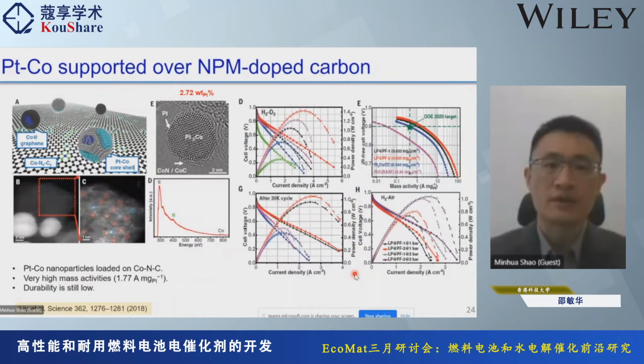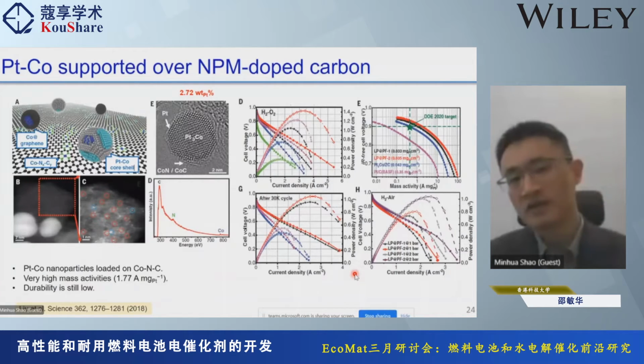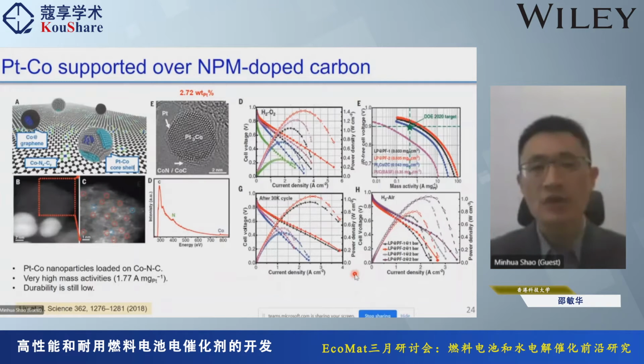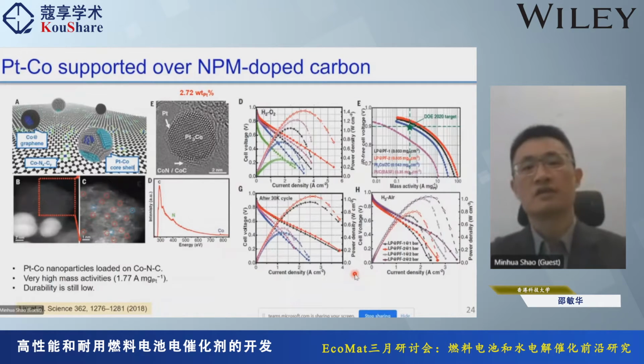So we're using this iron-based non-precious metal and platinum iron nanoparticles. So even though the iron-based non-precious metal has worse durability than cobalt-based nitrogen carbon catalyst, surprisingly, the hybrid catalyst based on iron actually has much better durability. So I'll talk a little bit more about it.